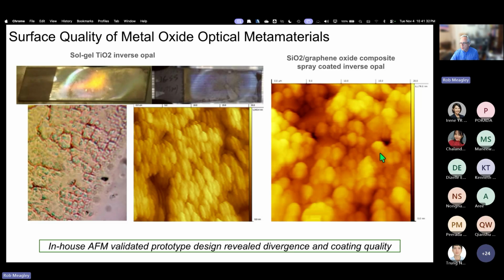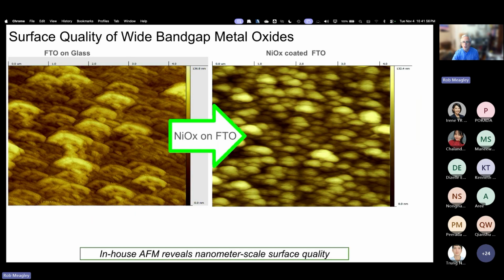And again, these spheres are about half micron, and I think we're getting somewhere around 35 or 40 nanometers of resolution, despite that extreme topography. Once again, we're validating the prototype design specs were met, and we were able to see that our low-cost coating solutions and our chemistry were doing exactly what they were supposed to do.